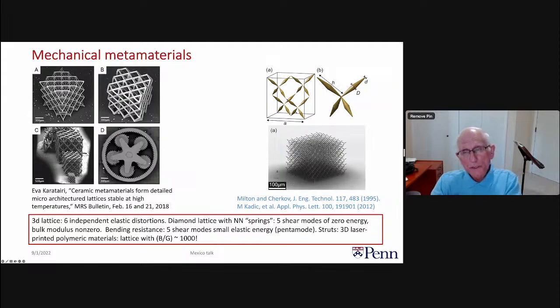This is a diamond lattice, and it's constructed so that the struts here are thicker in the middle and thinner at the end. And this gives it a lot of compression strength and a fair amount of flexibility at the node. So this is what the engineers call a pentamode system, because of the 6 elastic modes that you can have in 3 dimensions, 5 of them are soft and would vanish altogether if there were no bending restoring force there. However, the whole lattice resists isotropic compression under pressure. And you can see you can play frivolous games here, and some of the frivolous games are relevant to what we want to talk about today.